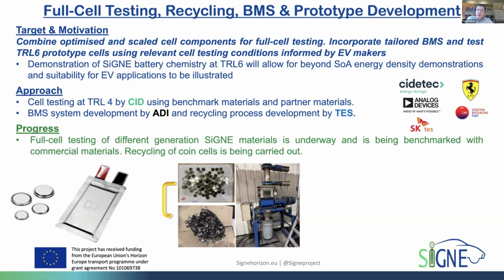So they have really delivered lots of nice data along the way, allowing us to benchmark these different generations of materials and kind of iron out some of the compatibility issues before we move up to the larger scale. So they are also coating the electrodes for our cylindrical cells, which will be used in the demonstrator at the end. Within SK tes, they're doing the recycling of these materials. So even taking the old coin cells that we would have made in the lab and trying to extract out the materials from them.